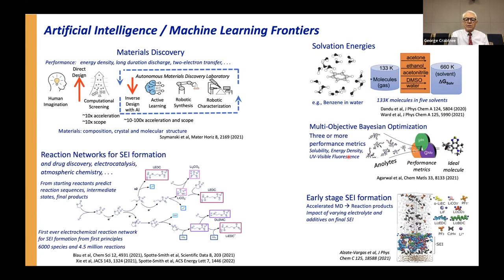I think I'll skip that one and that one. This is maybe the most interesting one. It's taking a given set of reactants and asking how many reactions can these two reactants participate in. So it's a cascade, but of course the products of the first reaction become the reactants of the next step in the cascade. And what do you finally end up with? The test they looked at was, let's try to predict the SEI formation in a lithium ion battery now because we know a lot about that SEI. And indeed, they were able to predict what you would get out and verify it with what we already know about lithium ion batteries. So this particular exercise involved 6,000 different species in the cascading reactions and 4.5 million different reactions.